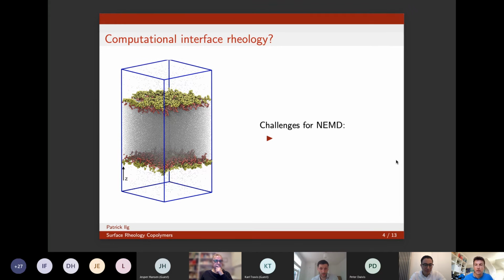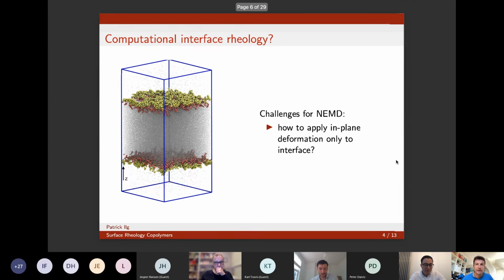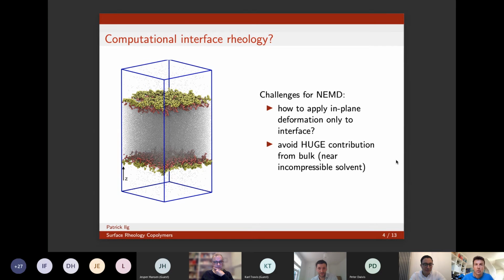So how can we do that with non-equilibrium molecular dynamics? Well, the challenge is we want to apply just the deformation in the plane. Yeah? So only to the interface. Why is that important? We want to avoid the contribution from the bulk. And the problem is that the bulk contribution is huge. Yeah? Because you have way more material, and typically what you measure is dilatational moduli. And so the bulk being nearly incompressible gives a monstrous huge contribution compared to the tiny one from the interface.